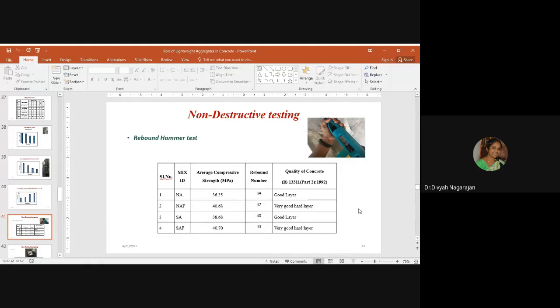The sintered fly ash aggregate concrete has a very hard outer layer, and the rebound hammer test is the proof for the same. The rebound number is high for the sintered fly ash aggregate concrete, and the average compressive strength was also a little bit higher when compared to normal aggregate concrete.